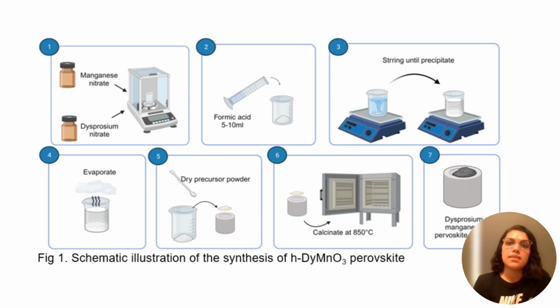Dysprosium manganite was synthesized by the precipitation method, employing dysprosium and manganese nitrates along with formic acid as a precipitation agent. The dry precursor was annealed at 850 degrees Celsius. The materials were characterized by X-ray diffraction, transmission electron microscopy, Fourier transform infrared, and UV spectroscopy. Photocatalytic degradation of malachite green dye was successfully induced under artificial light with a wavelength of 405 nanometers and an irradiance of 100 milliwatts per centimeter squared.